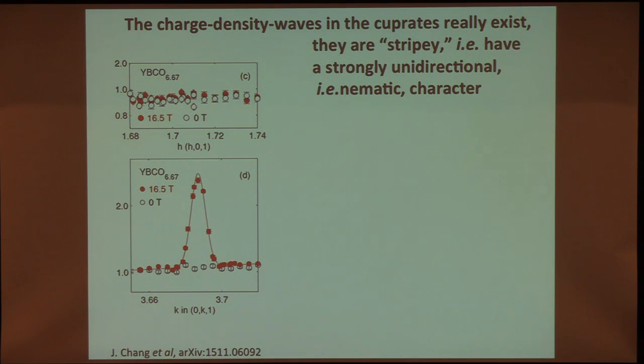This is a recently posted paper by Johan Chang. What you see is that at 0 Tesla, there's nothing. And at 16.5 Tesla, there's a very sharp charge ordering peak. Now, can you tell us what the peak intensity means in this case?